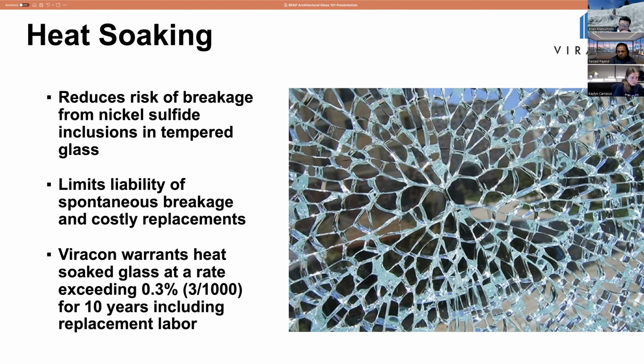So this nickel-rich impurity is going to be in that glass if it fell into the tank, and it's not going to be just one piece of glass. It's going to be throughout that batch, which is fine. If that glass is not tempered, no one will ever know it, and it'll be fine. Once you temper it, though, that little impurity has a little gas bubble around it. And tempered glass, as I mentioned earlier, is made by blowing large amounts of air on all the surfaces so that you're compressing the surfaces, and the core of the glass is in tension.